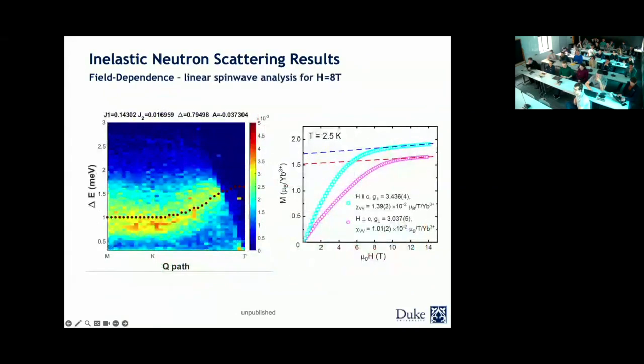We also went back and looked at the parameters that we proposed for the 1114, and tried to fit them to our data. One thing I would like to mention is that at 8 Tesla, this is 8 Tesla data, it's still not completely polarized. These dots show the simulation based on those parameters, and you can see they don't fit very well. There is a curvature in this higher field data set, and they don't agree very well.